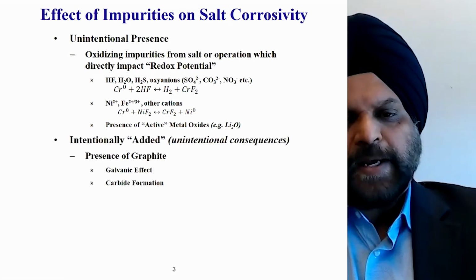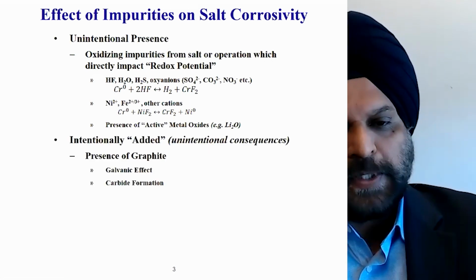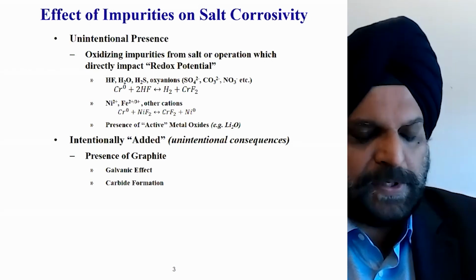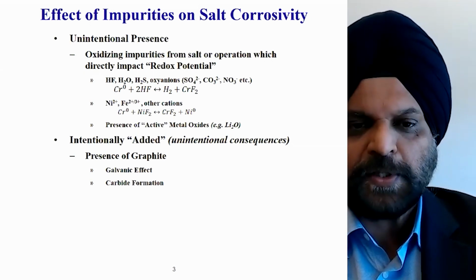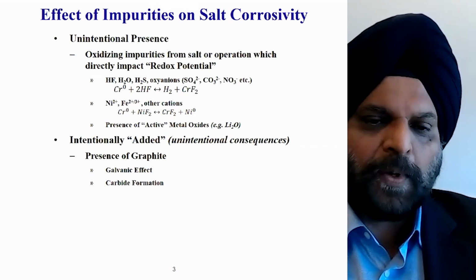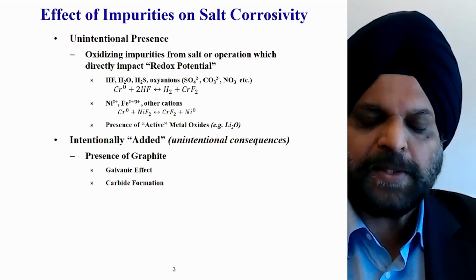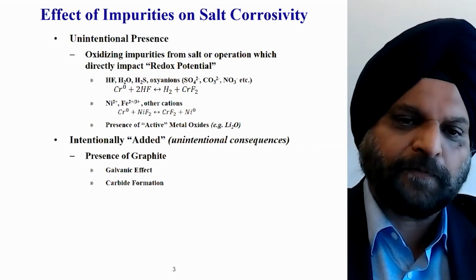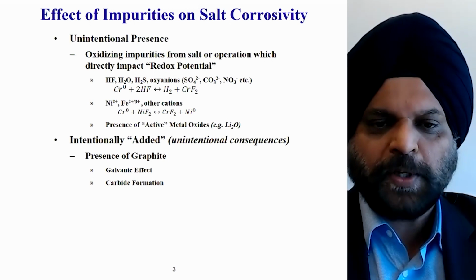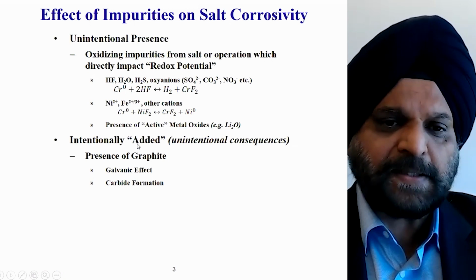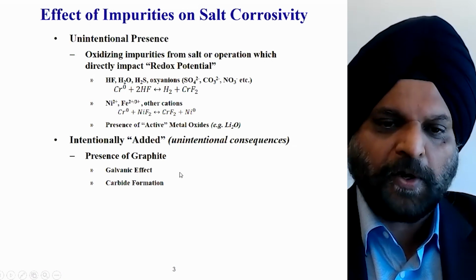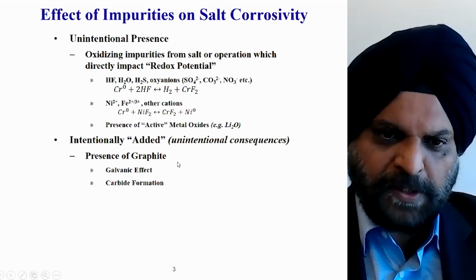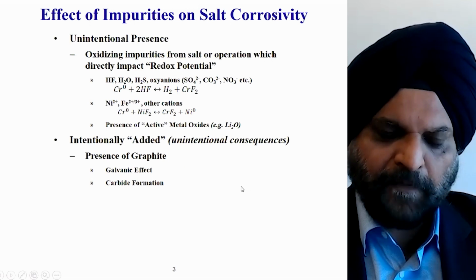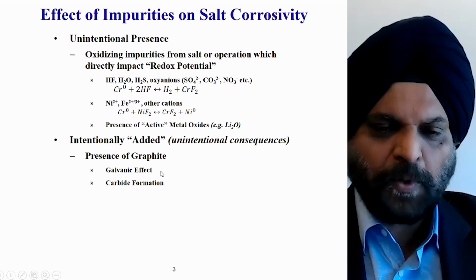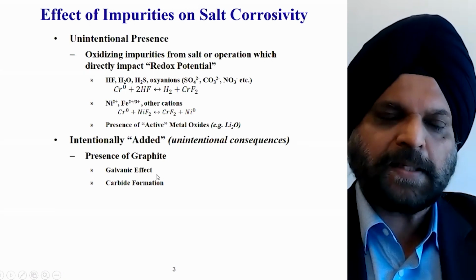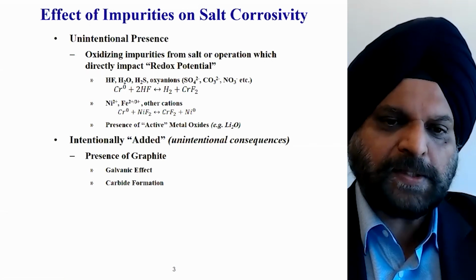Then there are intentionally added impurities, but with unintentional consequences. This is where it relates to the first talk in this session on graphite, where we know that in MSR designs, graphite is going to be one of the major structural components. Its intentional presence is also affecting corrosion of alloys. Some of the work at the University of Wisconsin has shown that there can be a direct galvanic effect. In fact, our work has shown that if you do tests in a graphite crucible versus a nickel crucible,